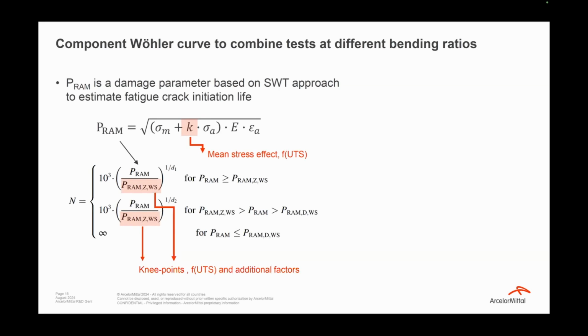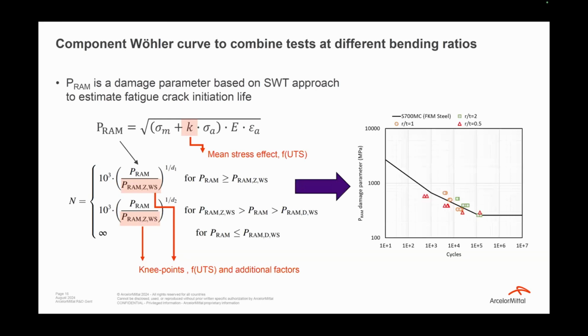Just it's important to know that this is also a function of the ultimate tensile strength. And then you can come up with a certain curve, again with two different knee points, which are also functions of ultimate tensile strength. And once we construct the curve, then we can put our points with the calculation. So at the first glance, it was interesting to see that the R over T 0.5 was really below the calculations.